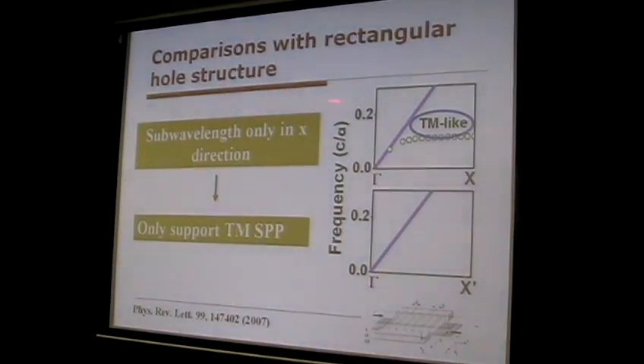Now let me compare the structure with other structures. This is another structure which was proposed 2 years ago by another group. They proposed that we do not use the square hole, but rather use rectangular holes. And they found that this system can support TM polarized surface plasmons without using high index materials, which is good. However, the limitation is that this structure only supports TM polarized surface plasmon along this direction. It cannot support any surface plasmon along these directions.